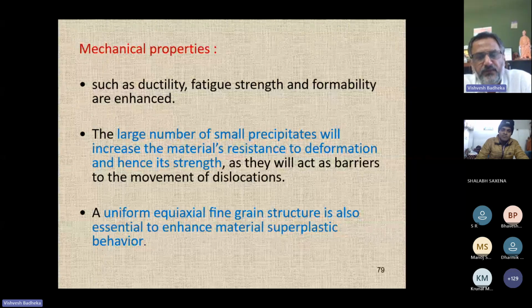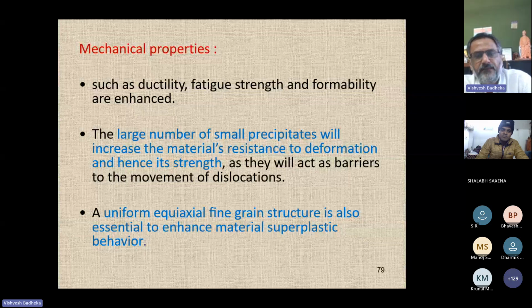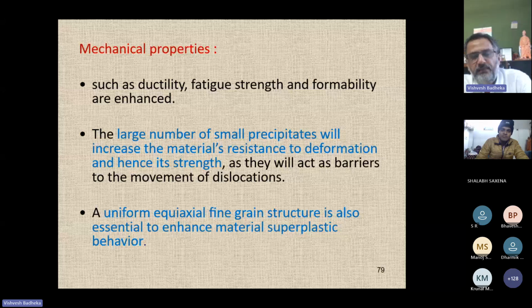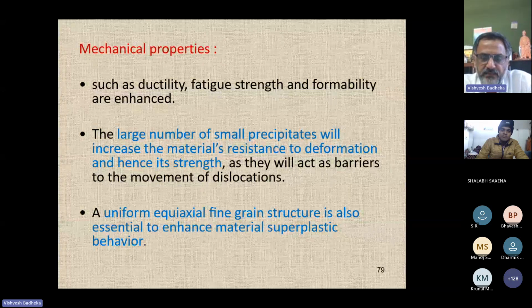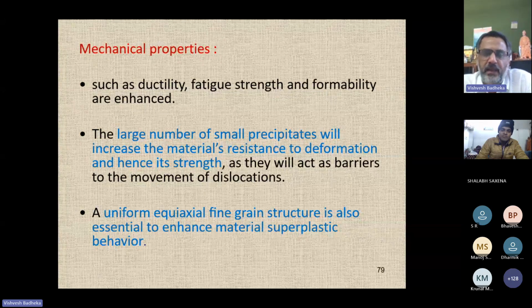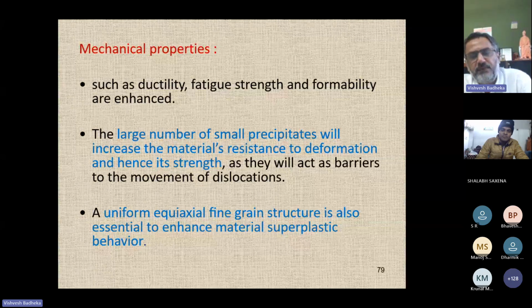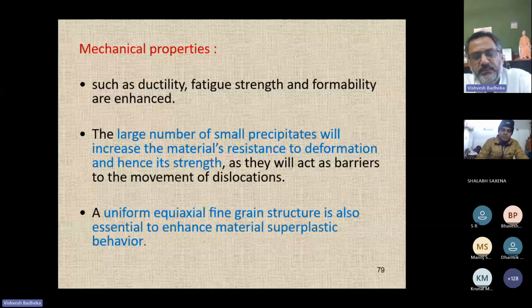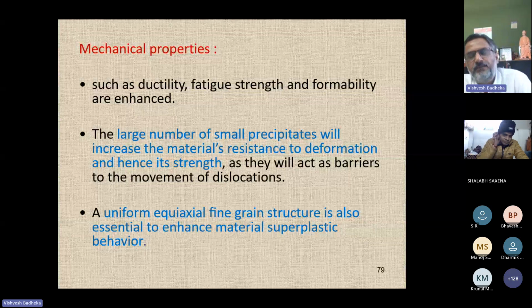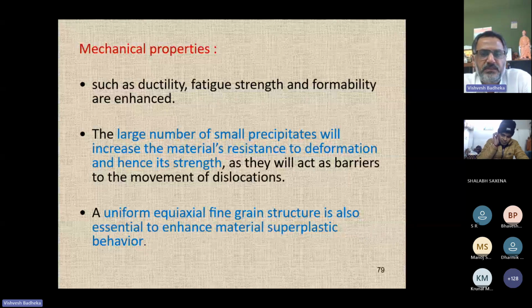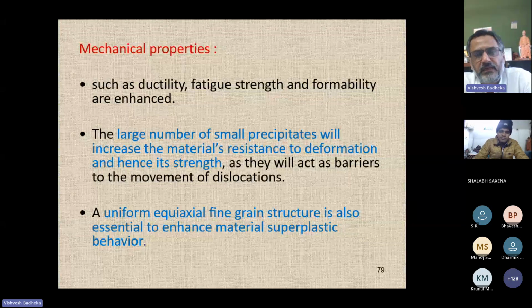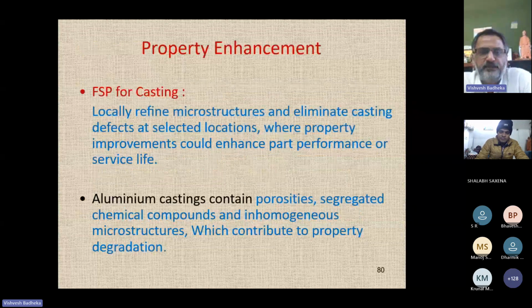Now after FSP, what will happen? The grain also gets refined, right? Those large precipitates get fragmented and become fine precipitates. And these fine precipitates act as a barrier to dislocation motion. And this uniform equiaxed fine grain structure is also essential to enhance the material's superplastic behavior. So these are the mechanisms responsible for the improvement in the mechanical property as well as the metallurgical property which we have discussed.